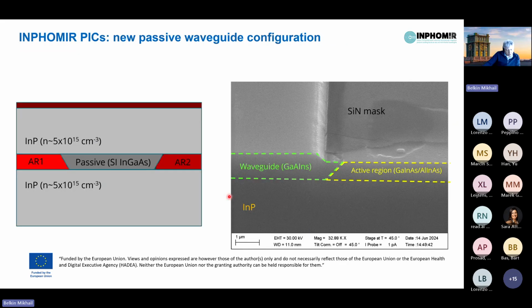For the INPHOMIR project, we followed a slightly different approach for photonic integration. This is because our photonic integrated circuits for the INPHOMIR project are going to be more complex. And so here, after growing active region 1 and active region 2, maybe active region 3 even if necessary, we selectively remove them, and then using metal organic vapor phase epitaxy, similar to what Javier talked about in near IR, we fill the gap with the semi-insulating iron-doped indium gallium arsenide waveguide.